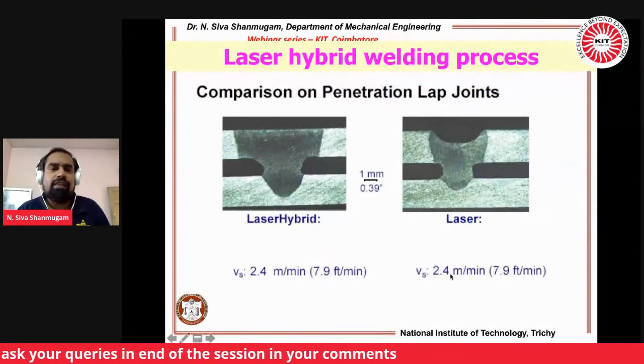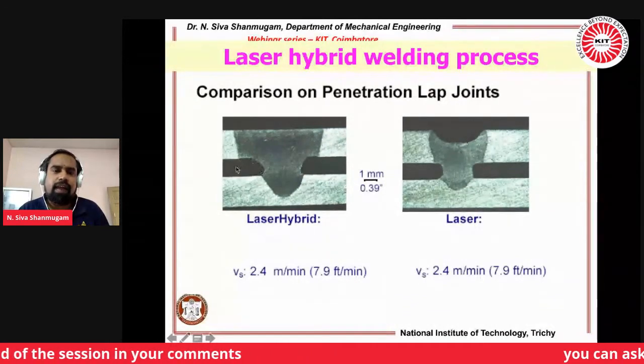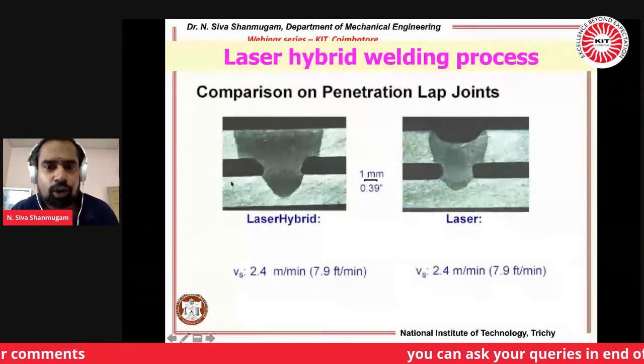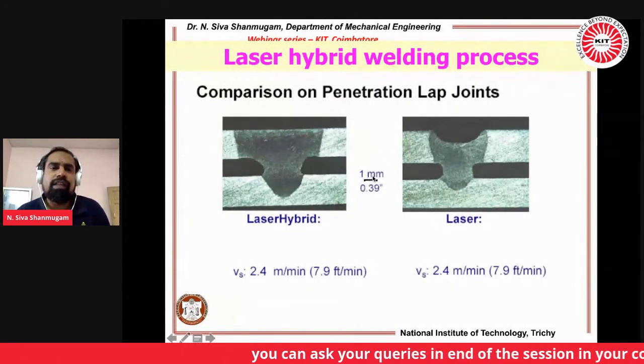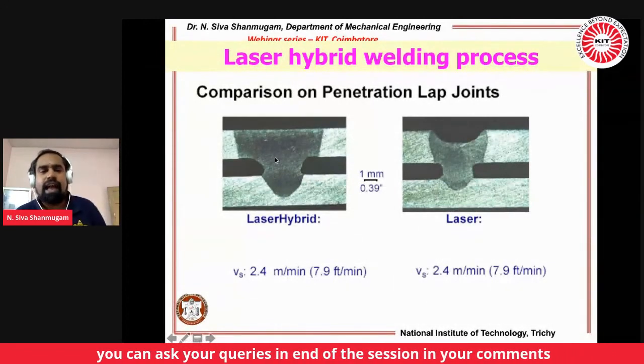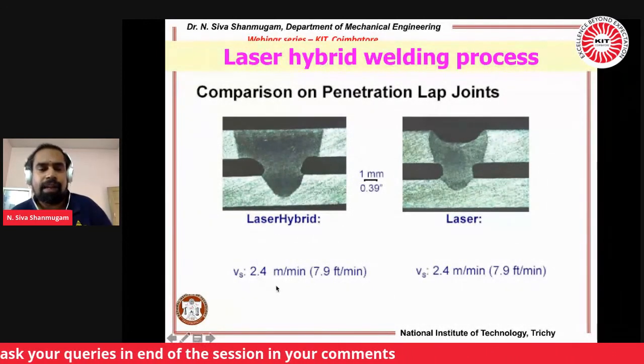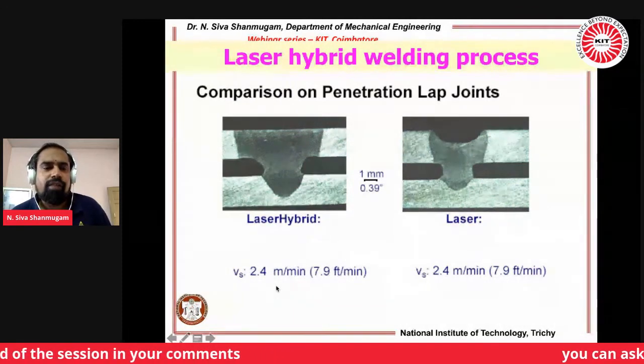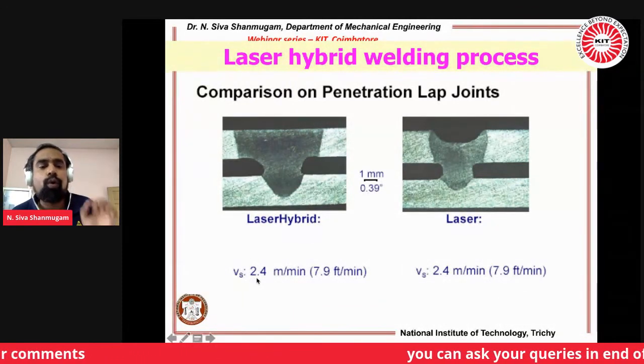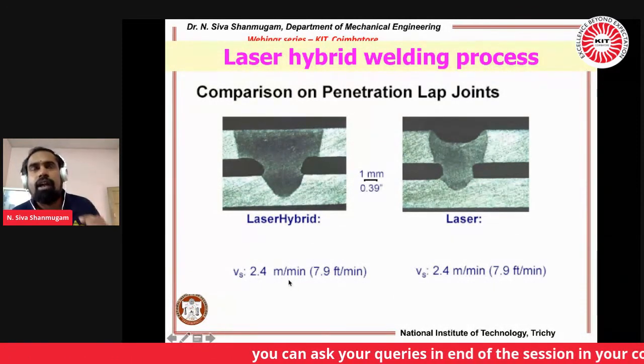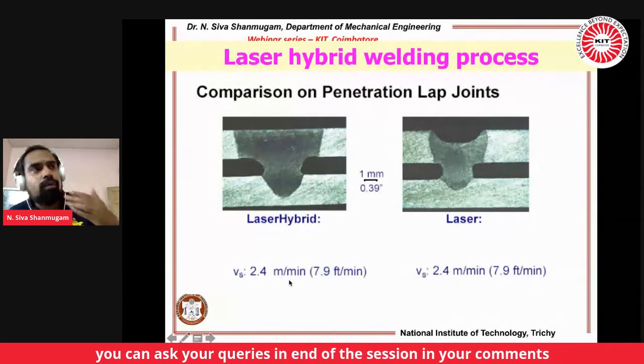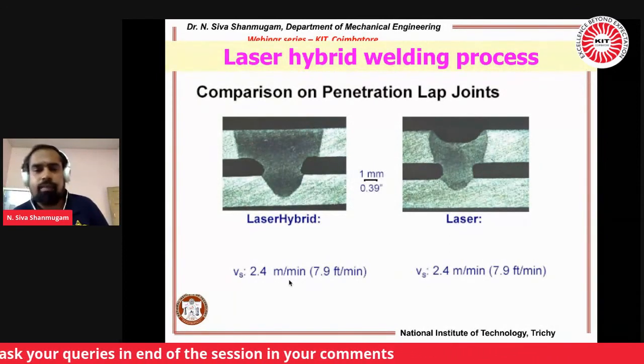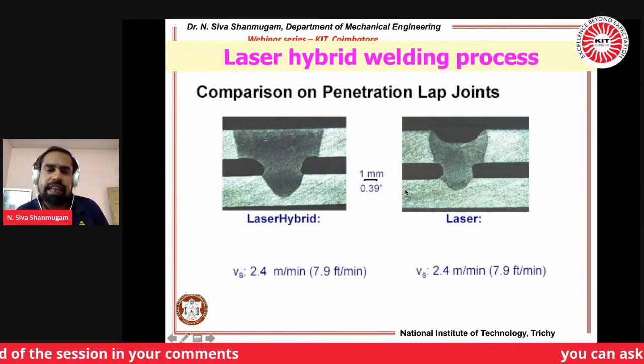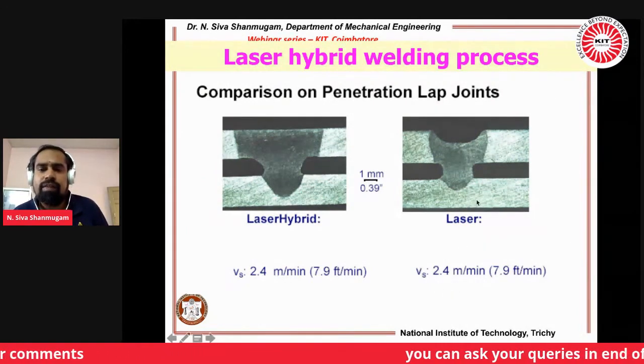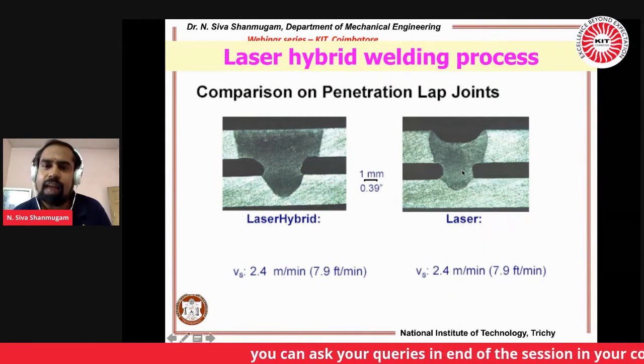You see, with the laser, even though the gap is very high, something around 1 mm, with the help of the laser hybrid technique, the parameters are also indicated here. Welding speed is maintained at around 2.4 meters per minute. For 60 seconds, it moved around 2400 mm. And with the same welding speed, with only the laser, you are not getting the gap bridgeability.